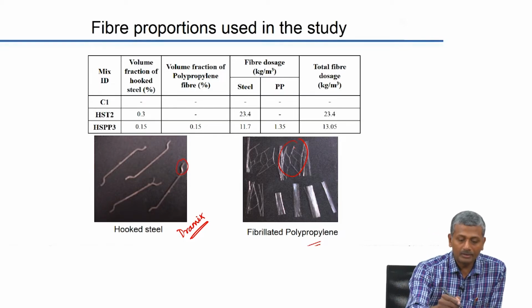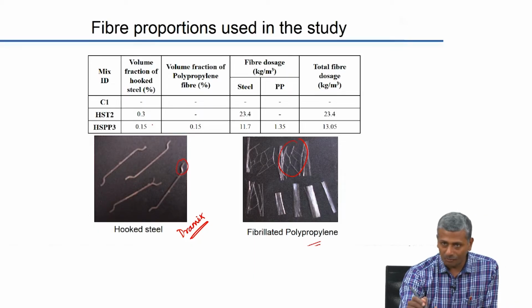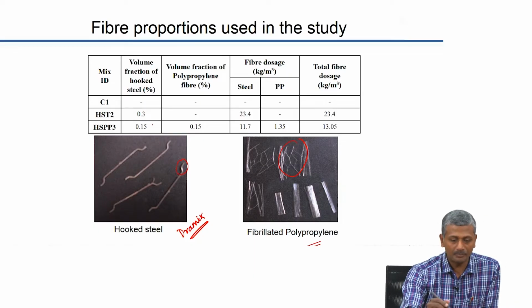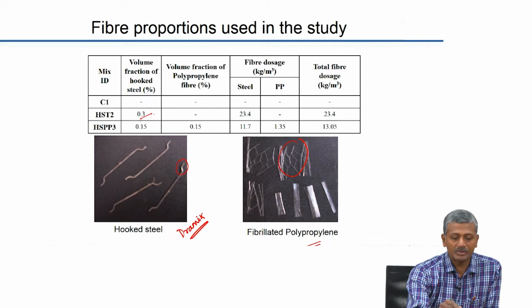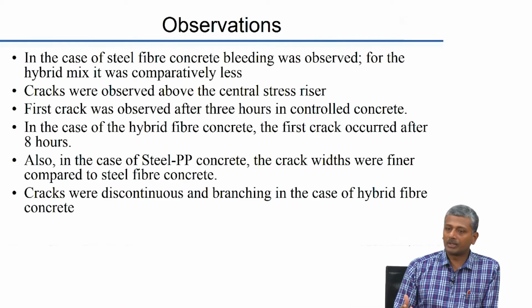Okay. And the dosage being discussed for this chapter looked at hooked steel fibers at 0.3%, and then a 50-50% combination of steel and polypropylene, which accounts for about 0.15% of each type of fiber.